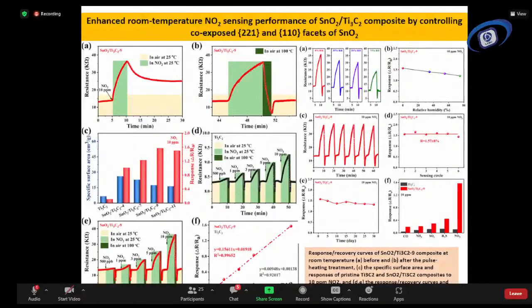It has given a better response than the previous one. You can see in figure A and also in figure F. It shows again maximum response for nitrogen dioxide gas, and the response was 1.6. Of course, the result looks very small, but this is the percentage response. That means the response was about 160, and this response is also very ideal. Different concentrations and different curves are shown in the figure.